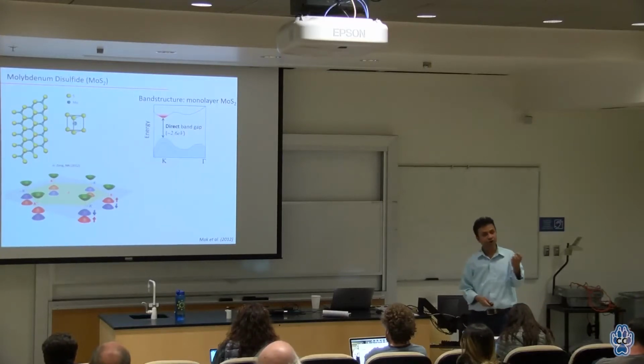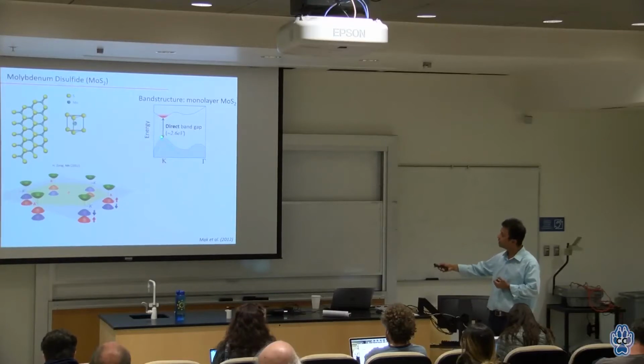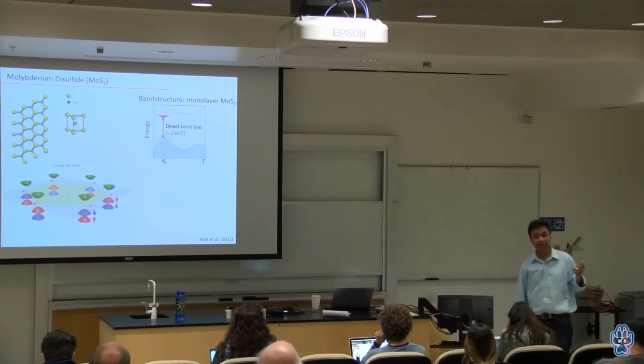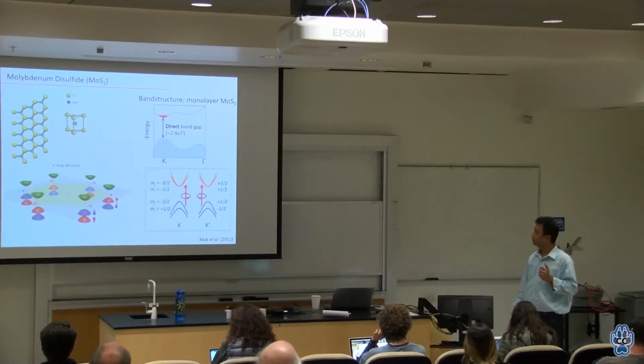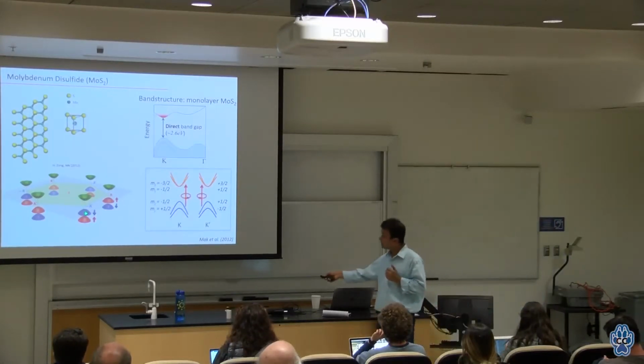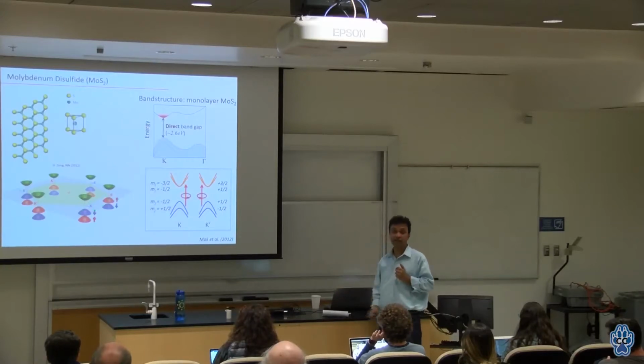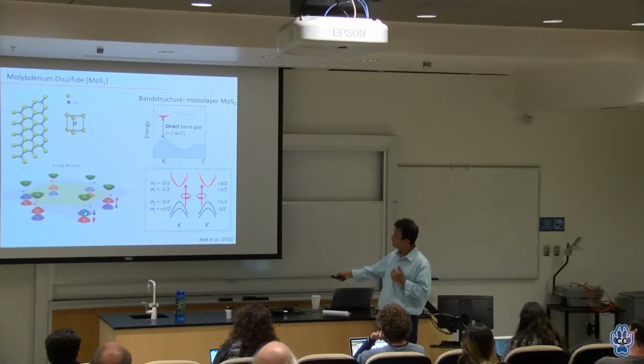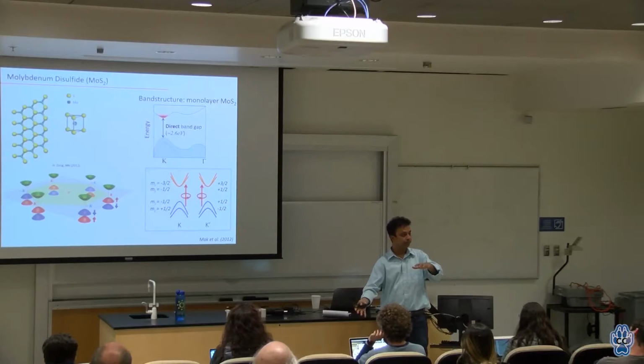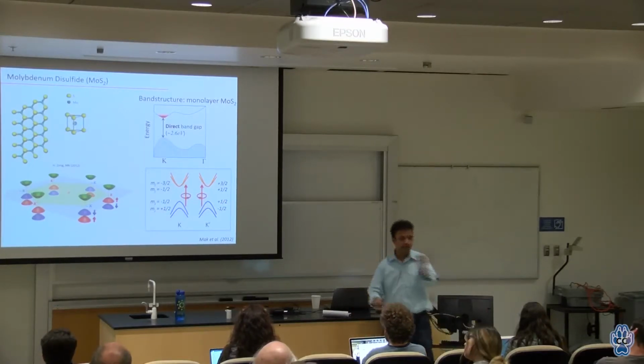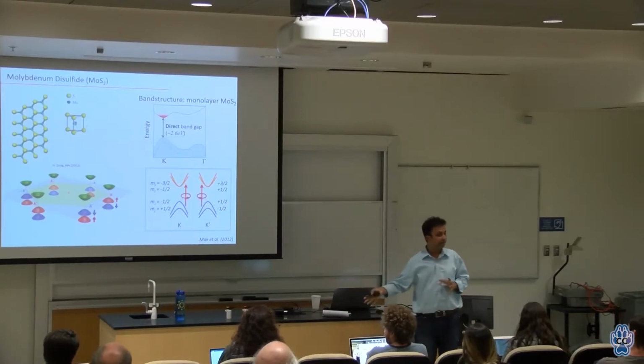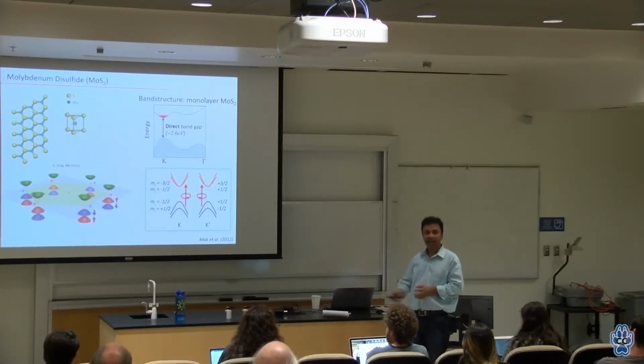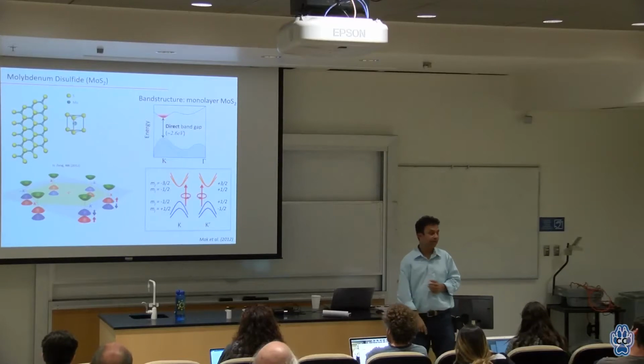It also has a very strong spin orbit interaction. That means your valence band splits here, on the order of 160 meV, so you can observe it even at room temperature. Not only that, it also has these quantum properties called valleys, K and minus K. Note that at the minus K point, the blue is sitting at the bottom. So the electron at this valley cannot just travel to here, because it's sitting at the bottom. So you will have a way to create carriers, electrons, with this certain quantum behavior.